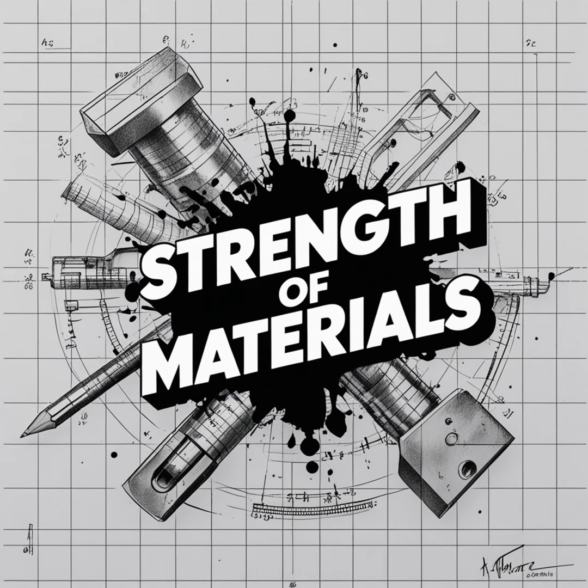Now, I can visualize that, but does this actually slow the crack down? I mean, geometrically, it has to travel a slightly longer total distance because it's zigzagging instead of going in a straight line. But is there a physical, mechanical benefit to the deflection? Yes, a massive one. It's not just about the distance. When the crack deflects and tilts away from the primary plane of stress, the effective stress intensity at the very tip of the crack is mathematically reduced.